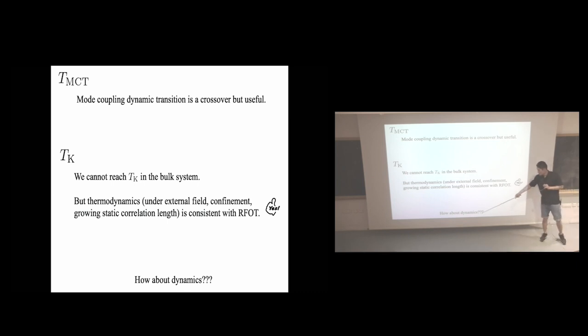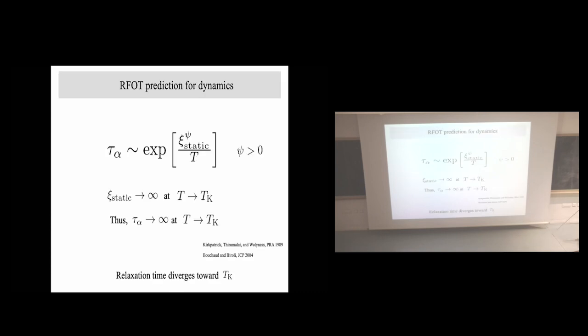So the next obvious question is, how about dynamics? Okay. So in a nutshell, random first order transition theory predicts that the relaxation time scales as the exponential of the static correlation length to some critical exponent psi. And the theory predicts that this static correlation length diverges toward the ideal Kauzmann transition temperature.